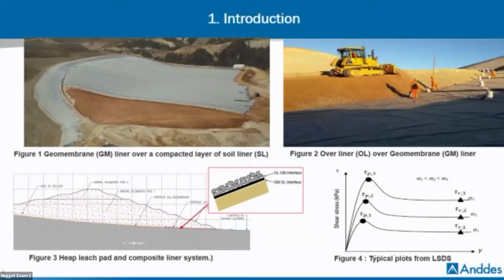One of the main restrictions of geotechnical design of heap leach pads is related to the strength of the liner system, which usually provides at least two interfaces: a soil liner with geomembrane, or geomembrane with overliner, both with low shear strengths due to the contact with the geomembrane. This interface can also control the stability of the liner. The shear strength of the interface is measured by a large-scale direct shear test.